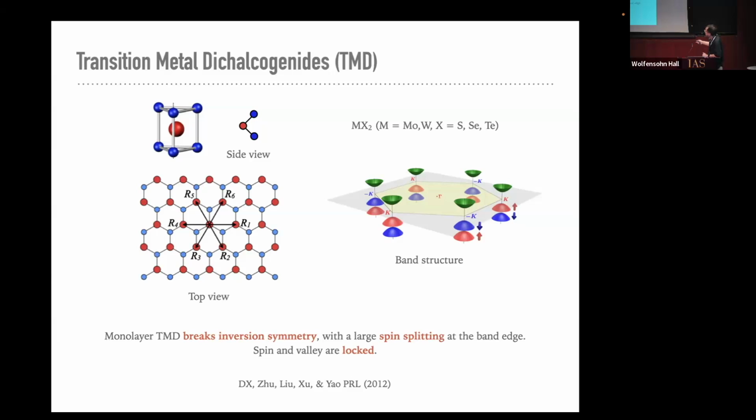But in the TMD, because of the spin valley coupling, it gives you the simplest system you can study. Okay. So then, as you can see from the experiment, the most interesting physics really happens when you dope the valence band. And because this is, as I said earlier, roughly on the order of 1 eV, and this is roughly on the order of 200 meV, you can ignore all those conduction bands and the valence bands below. Just look at the valence band top. Okay, so that's the basic information about the monolayer TMDs in terms of their structural and electronic properties.